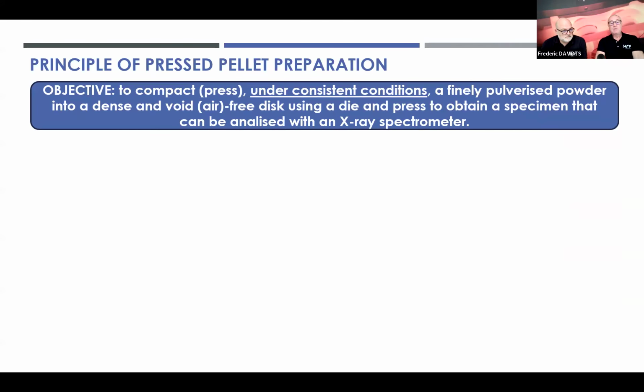A sample in its purest form is always the best, and we can obtain really very good, high quality results. Now, it is very important that we press the sample, that we compact the powder under consistent conditions. This means we always want to use the same conditions, same dilution, same everything. And it is a finely pulverized powder that we make into a dense and void-free disc using a die and the press to obtain a specimen that can easily be analyzed with our X-ray spectrometer. So read also here, void, air-free. This means that by making this compact disc, we are losing the air that in general we have in between the grains of our sample.